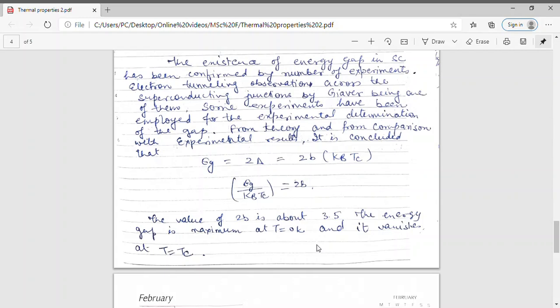The presence of this energy gap in a superconductor has been confirmed by electron tunneling observation experiments, which were carried out by Giaever, and many other experimental determinations have been done to prove the presence of this gap. From these experiments and comparison with the theory, it has been found that this gap, which is denoted by Eg, has a value equal to 2B kB Tc, and this gap can be written as equal to 2 delta.